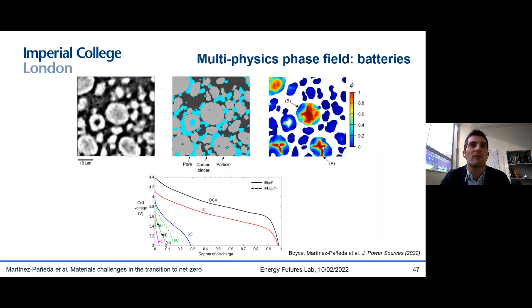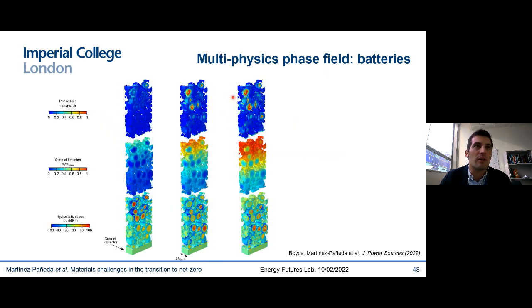Here a 2D section with the various phases and basically the fracture predictions. And these are 3D results showing lithiation, fracture, and basically showing how the electrode exhibits a highly heterogeneous electrochemical and fracture response, which depends on the particle size and the distance from the separator and the current collector. So we have a tool that allows us to evaluate the electrochemical performance and damage behavior as a function of discharge rate, electrode thickness, and the cycling voltage window.